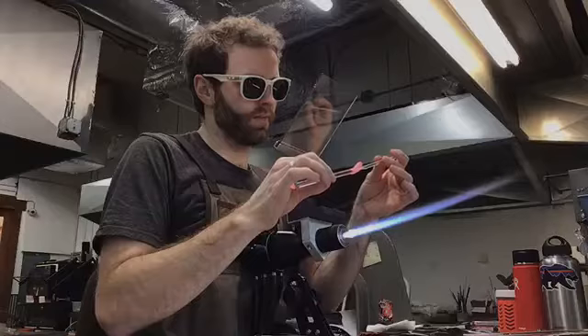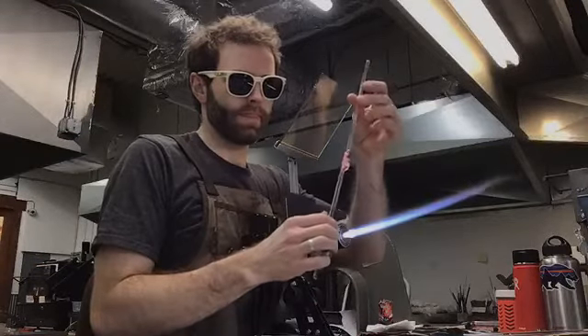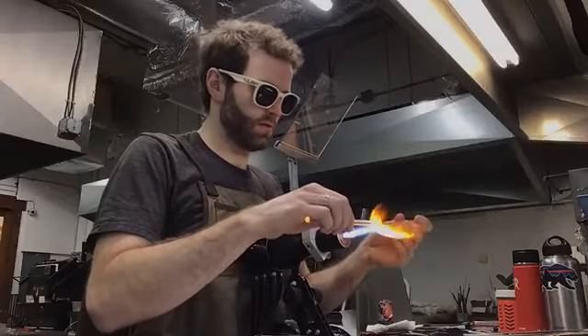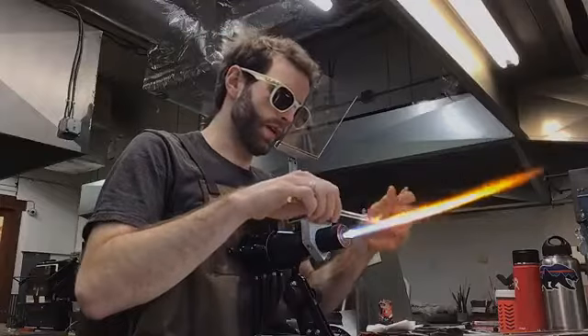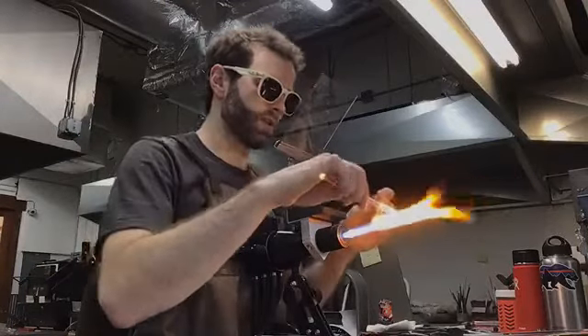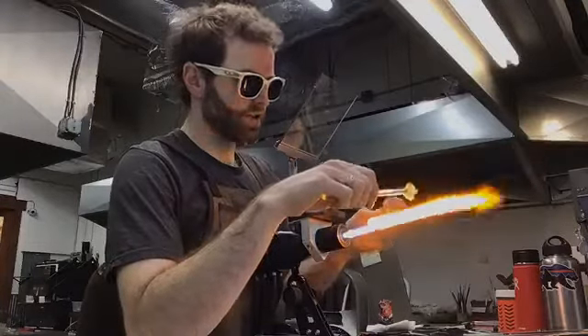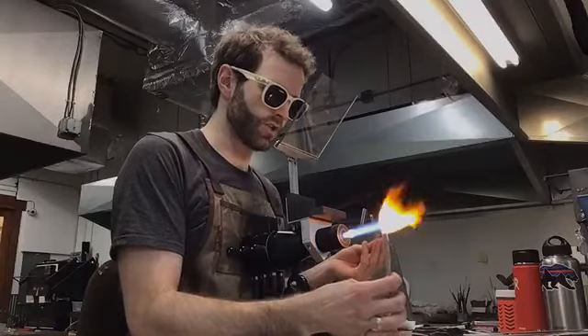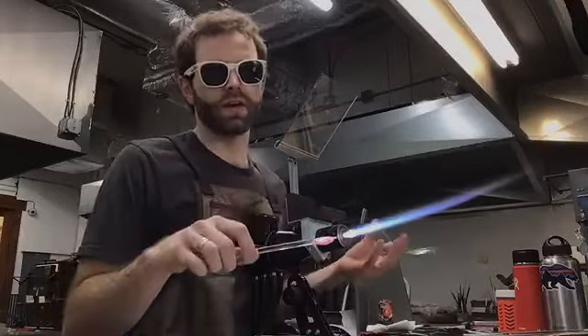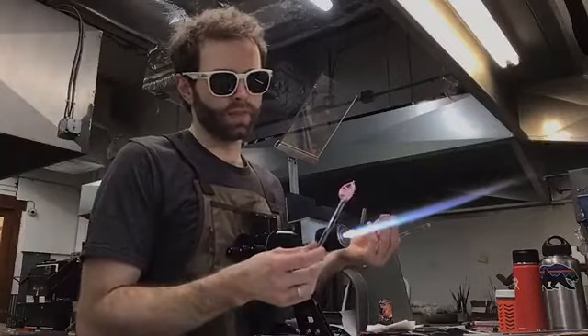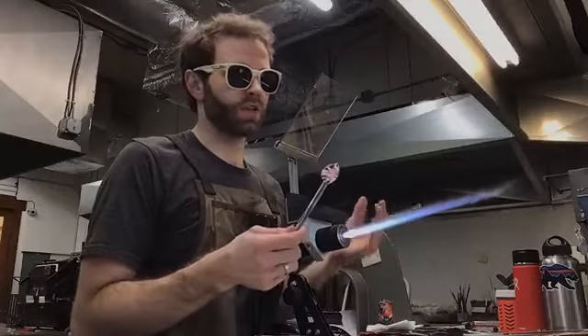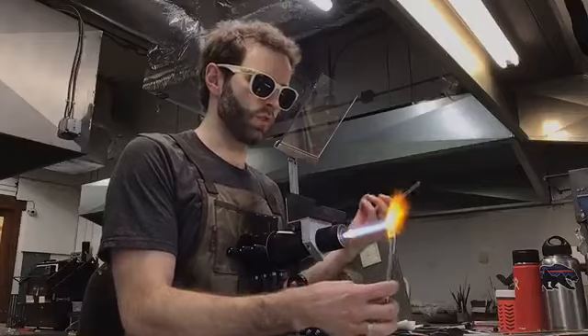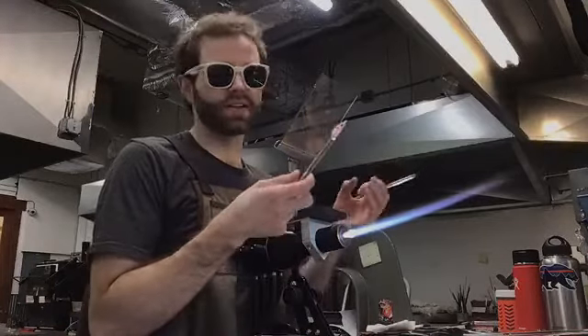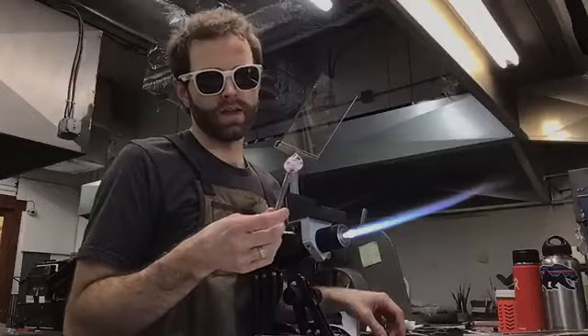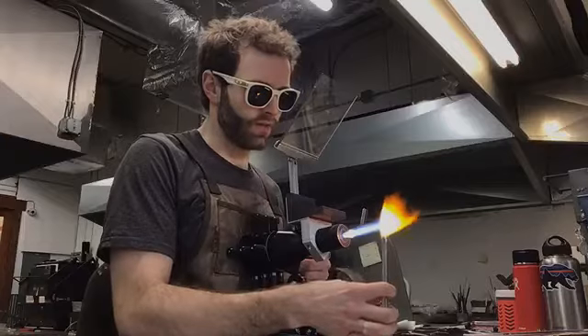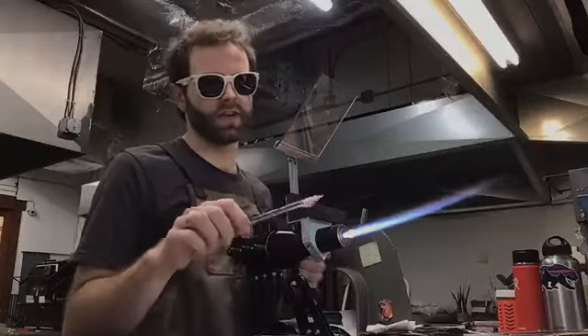So we'll stick the punty on to stretch out the tip. Give it a little stretch. When I'm heating the leaf to get it stretched, I'm also doing something else. I'm polishing the leaf. The mashers tend to leave little wrinkles on the surface of the glass, because as soon as that hot glass touches the steel tool, it starts cooling immediately. But the glass underneath that is still hot enough to move. And so you get these little wrinkles, they're almost like stretch marks, where the surface glass doesn't really want to move as much as the glass underneath it does. And so that's why you always want to polish anything you've touched with a cold tool, whether it's steel or graphite or anything like that.